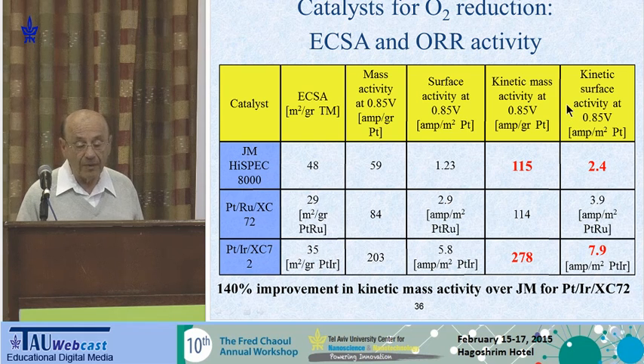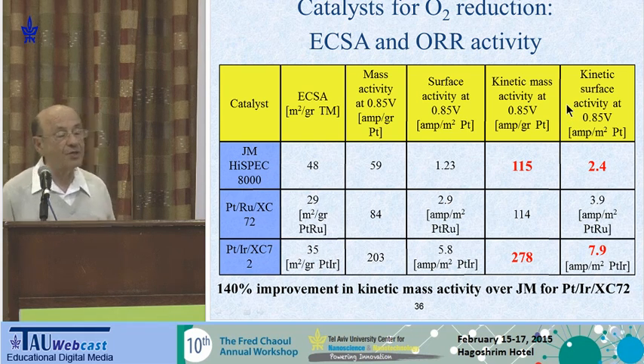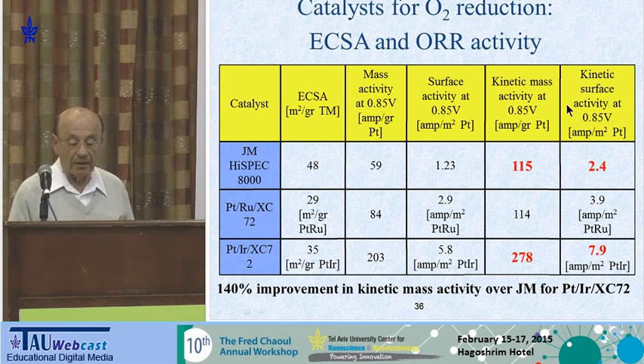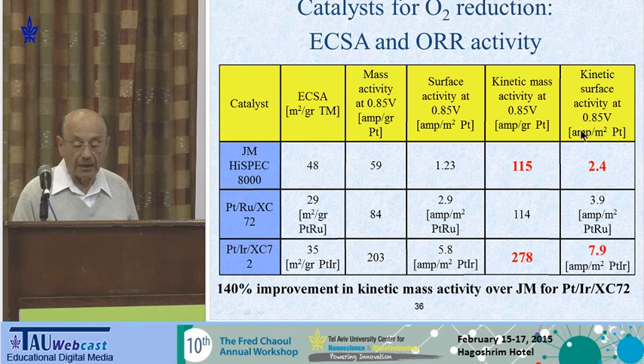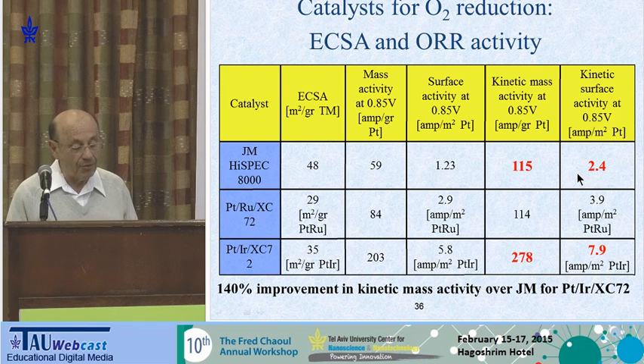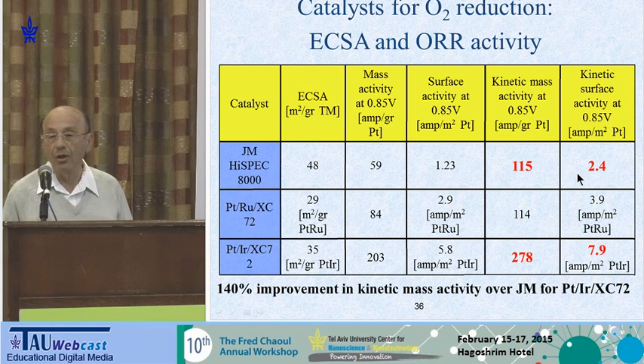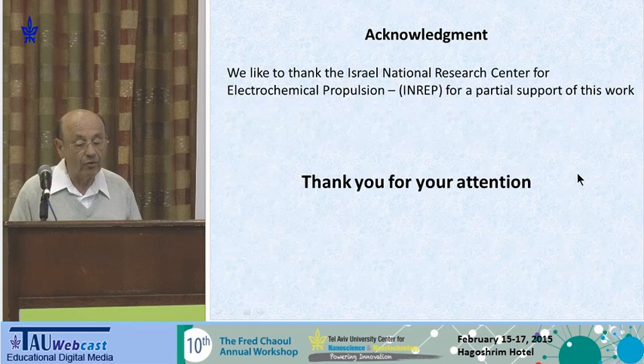Now, the scientific parameters are the real activity and the surface activity. What is the surface activity of this catalyst? When we measure the activity in terms of ampere per square meter, then you see the kinetic ability of the catalyst. And again, our catalyst is 3 times more active than the HiSPEC. So for the platinum that we deposit in a submonolayer on iridium, we get better catalytic activity. That means there is better catalytic activity from the combination of iridium underneath the platinum or nearby. And thank you for your attention.